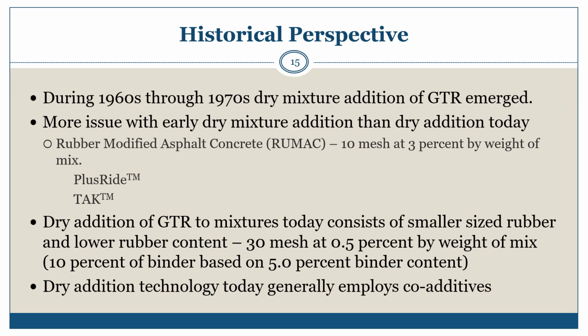The primary difference in the dry process technology of the 1960s and the 1970s compared to today's dry process technology relates to GTR particle size and dosage, where in the earlier versions, 10 mesh rubber was used at a loading of 3% by weight of the mixture. And today, the mixtures consist of smaller size rubber of 30 mesh at about 0.5% by weight of the mixture. Additionally, co-additives that aid in mixing, placement, and compaction have been employed today. These additives have included processing aids from the tire manufacturing industry, Fischer-Tropsch waxes, and Stearamide waxes.